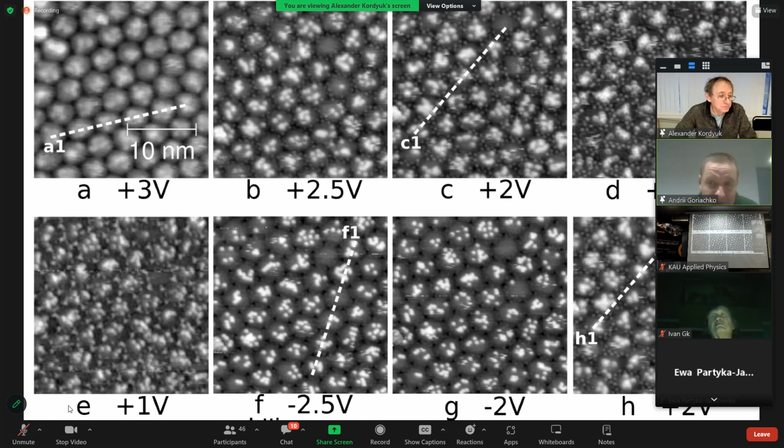It is proposed, but not proven, that the reason behind this is that the layer of germanium atoms just beneath the graphene is actually mobile at room temperature. That means there are a lot of vacancies, and as a result, there are a lot of configurations that the germanium atoms in the topmost layer can assume, and by this they change the local geometrical structure of the interface and the local electronic structure also.